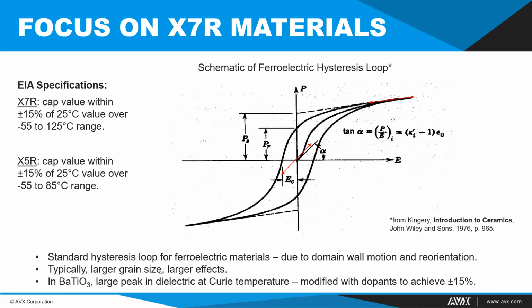Typically, larger grain size materials show larger effects of this type of change in dielectric constants. And so this transition occurs or begins to show up in the material, for example, in barium titanate at its Curie temperature of 125 degrees. So in order to make that material an X7R, a large peak occurs at that point, and what is necessary is to add dopants to actually flatten that curve out at that point. And so that's where the compositional work of making an X7R device comes from.